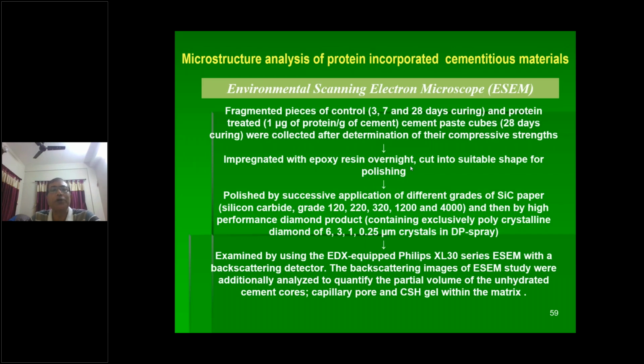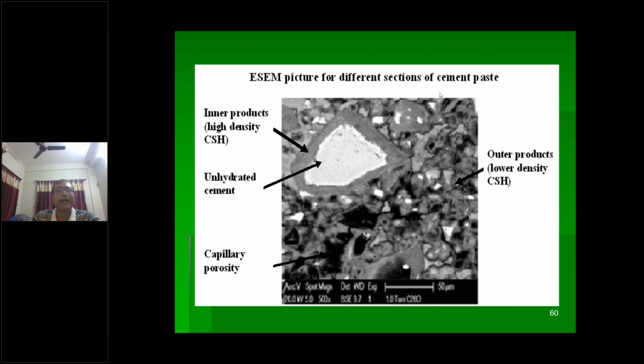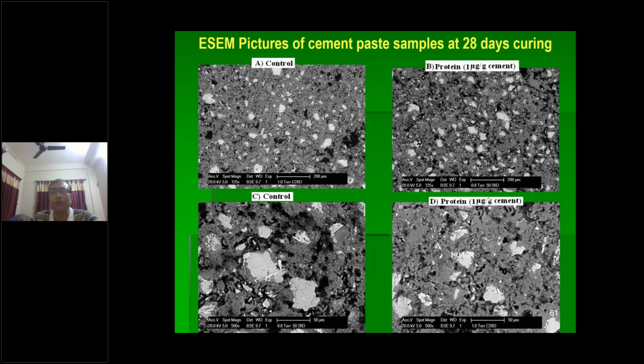Next, we did microstructure analysis of the protein incorporated cementitious material by environmental scanning electron microscope. What you see here is the unhydrated cement paste, then there is the C-S-H gel. These are capillary pores, and this is the outer product, a low density C-S-H. This is the ESEM picture of cement paste samples at 28 days, at different protein values. Somehow we are getting a more compact system in these cases.